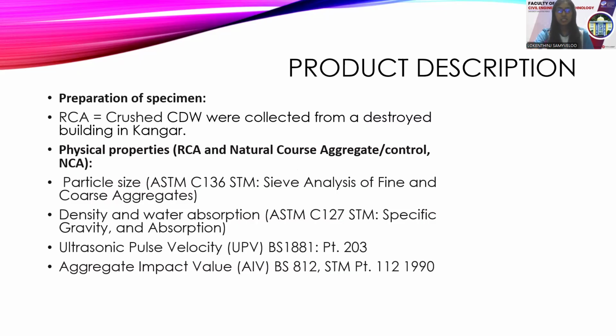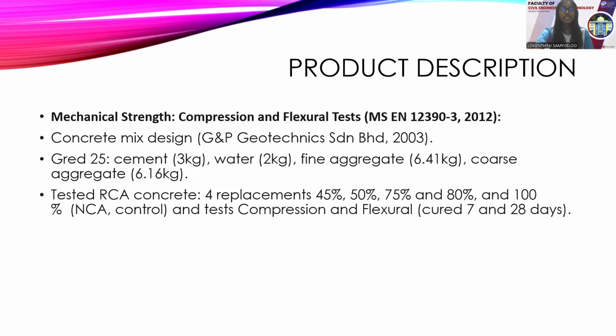Next, mechanical strength. It has two tests, compression and flexural test. Before we conduct the testing, first we need to calculate the concrete mix design. Second, we used grade 25, using cement 3 kg, water 2 kg, fine aggregate 6.41 kg, coarse aggregate 6.16 kg. And the third, tested RCA concrete, they have 4 replacement levels we used.